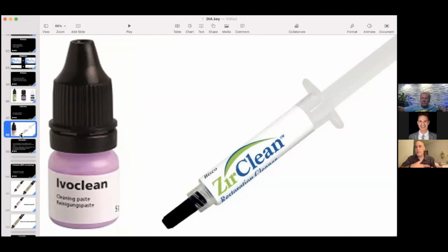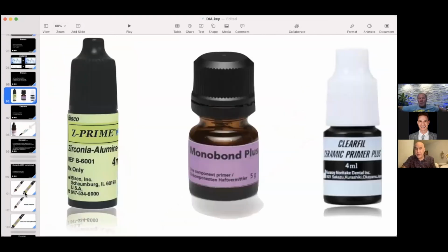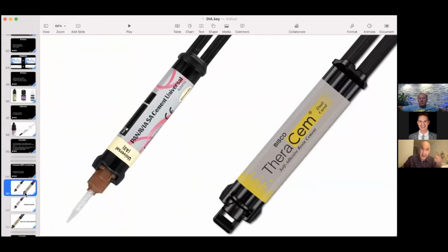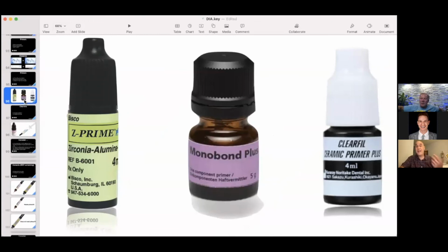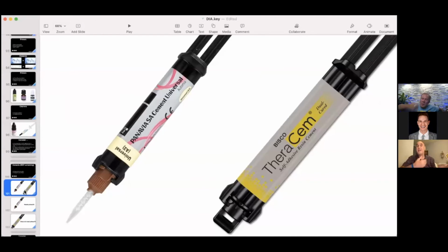All right. So if you're going to bond a crown, let's say, you can use your primer, but you can also use an MDP-containing cement for a crown or an onlay. In this case, you will not need to use the primer because the MDP is part of your cement. Due to the reaction of the MDP, this type of cement will definitely bond to zirconia without the need of an extra primer. Okay. So those are options. On a veneer, different story. You're going to use a light-cure cement that doesn't have MDP, so you need to use your primer, 100%. And if you're going to cement a crown but you don't have one of these cements, you need to use your MDP-containing primer in order to bond to zirconia.